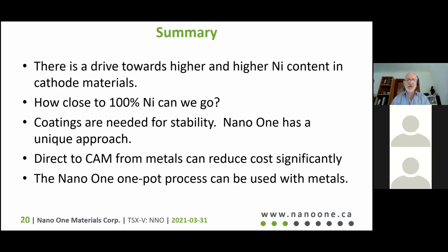So to summarize everything, what we've got is, in the drive towards higher and higher nickel content materials, there's a problem, because they're going closer and closer to 100%. They're up to 94-95% nickel right now. And everybody in the industry knows that 100% nickel doesn't work. So they're trying to see how close to the edge of the cliff they can get, to get higher and higher energy density, but that has an impact on durability, and the coatings are needed for stability.